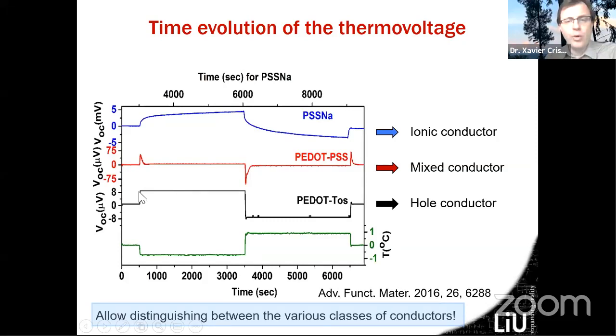Now, if you look at an ionic conductor, the PSS-Na is not conducting the electron, just the ions. What you see is there is also an increase of potential, open circuit voltage, when you apply the temperature gradient, but that one extends to huge values, close to 4 millivolts. So it's a much larger voltage promoted by the same temperature gradient, because these are ions.